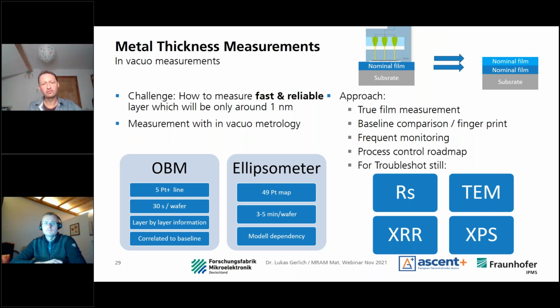So the challenge here is to measure very fast and very reliably in these desired ranges. And it's quite a fast method. You have only a few points, but it takes less than 30 seconds. So you have a true film measurement. You can always use an ellipsometer outside of the tool. You have a baseline comparison. You have frequent monitoring. And it's anyway in the process control roadmap.